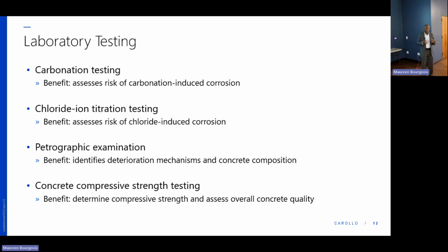Because when you pour the concrete over the reinforcing, the cement paste forms a very good barrier around the reinforcing. That is why it doesn't corrode, because there's a chemical reaction that takes place and it coats the reinforcing, preventing it from corrosion. What happens with chlorides is when you have just the right amount of chlorides in concentration, it will destroy that protective barrier. And then the moisture and oxygen are able to get in and begin to deteriorate the reinforcing. And so the testing in the lab uses various acids and chemicals to test the cores so that we can tell how much chlorides are in the cores, thereby indicating how much chlorides perhaps have affected the structure.